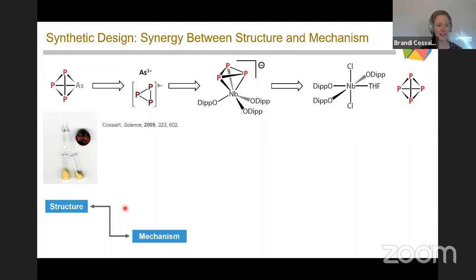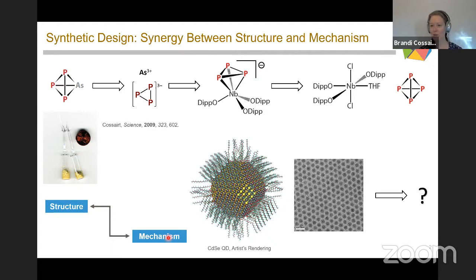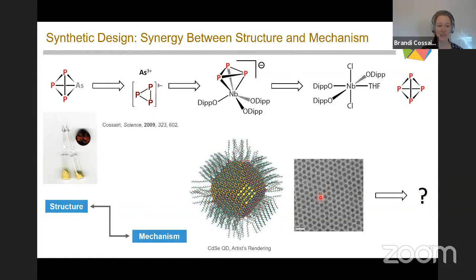As a synthetic chemist by training, this is how I think - there's this inextricable connection between structure and mechanism. When I got into this field, working with John Owen as a postdoc, I hit a roadblock right away: you can't really draw the atom-level structure of a quantum dot. We have some idea from electron microscopy that these things are composed of crystalline inorganic cores, but maybe they're riddled with stacking faults or have unusual structure types. We have some fuzzy knowledge of the surfaces, but we really don't know with atom-level precision what the surface looks like.